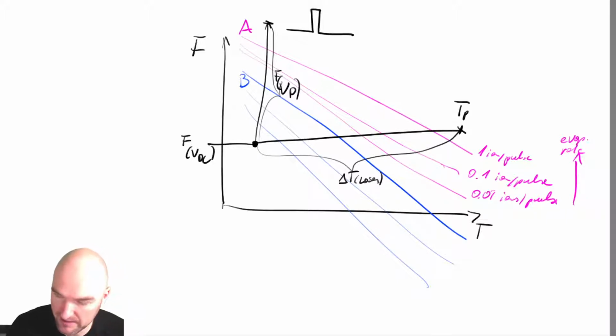This is going to be laser field evaporation, that needs to be high enough that the voltage pulse needs to be high enough that also we don't have the effect that we just evaporate one type of atom and the other one sticks. And the same thing about the laser power. We need to have enough laser power to evaporate everything and to raise the temperature high enough.